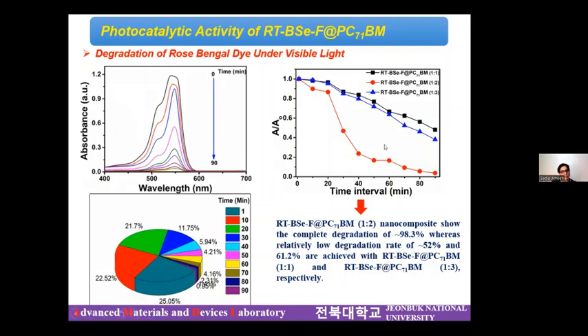So this is the brief description of the photocatalytic activity, that is, photocatalytic degradation of the Rose Bengal dye for the different composite materials. And we have obtained the highest degradation when the ratio was 1:2, and the degradation was like 98.3%, in just 90 minutes.